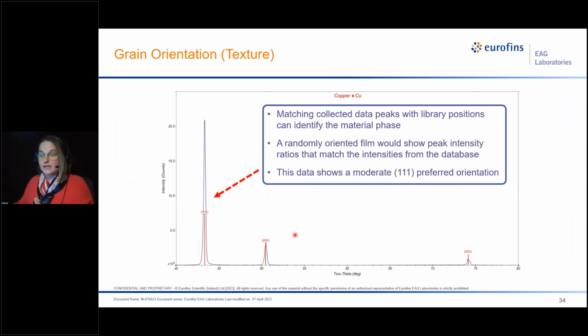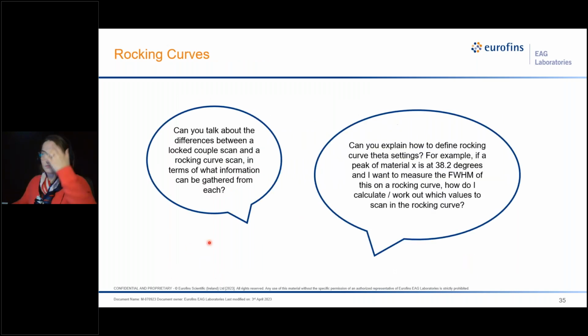So the most simple kind of texture analysis we can do is just preferred orientation, where the database phase is calculated based on the crystallites having perfect random orientation, whereas your sample may not be like that. And we can compare the ratio of the peaks in your sample to the ratio in the database and tell you which direction in hkl your material is preferentially oriented. So in this example, we have preferential orientation in the 111 direction.